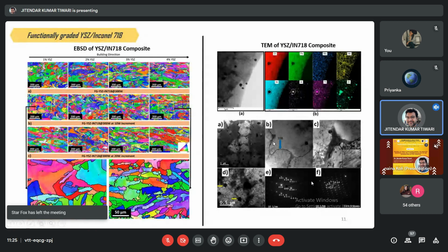Okay, and this SSB is the solidification subgrain boundaries. You know about the grain boundaries and the subgrain boundaries. This is very important to understand here. These spots are what we call selected area electron diffraction. The selected area electron diffraction is basically a diffraction pattern: the electron beam comes and interacts with the material, and diffraction occurs from different planes, and then it forms spots. So each spot represents a plane.